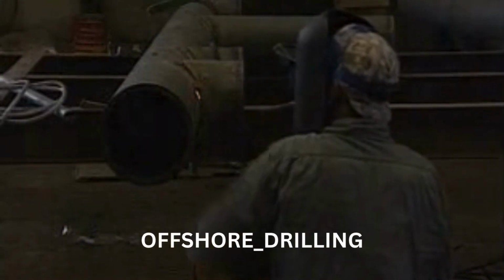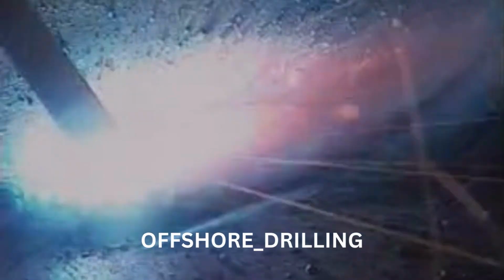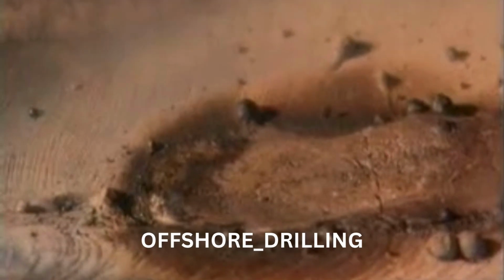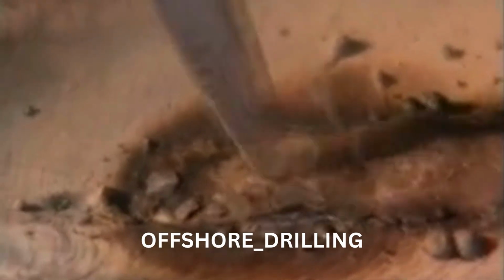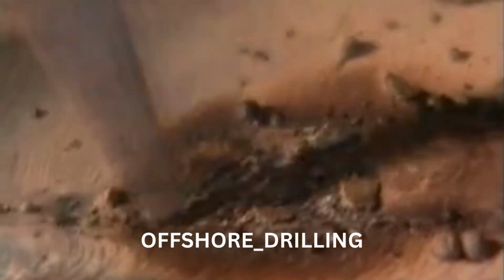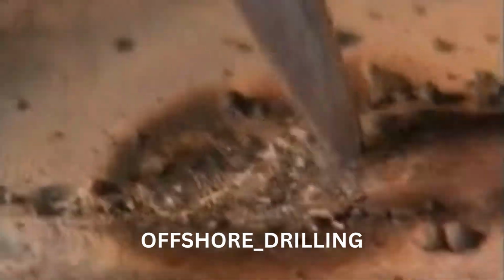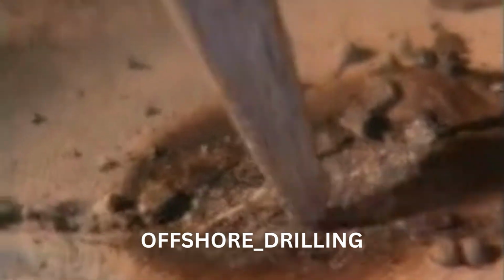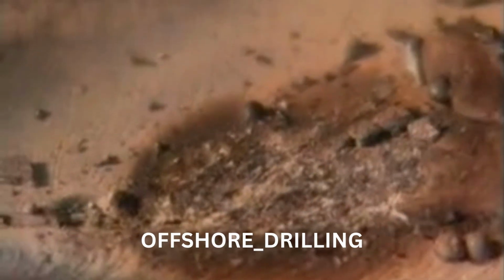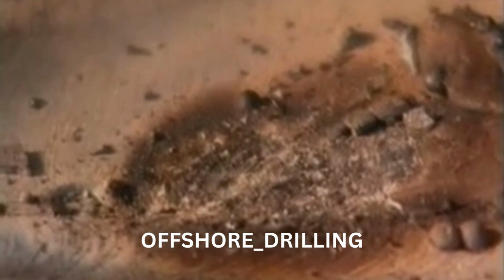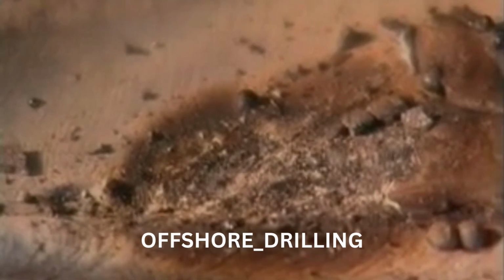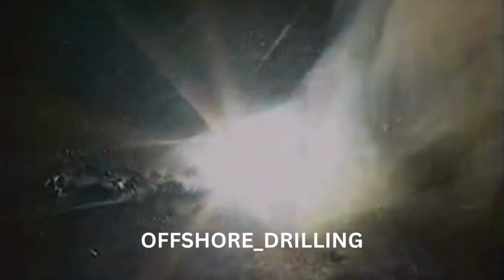Often, the electrode will be exhausted before you finish the joint. When you break the arc, it leaves a crater at the end of the weld, which can create problems. Because the crater contains less filler than the rest of the weld, it cools more quickly and can cause cracks to appear. Before you strike the next arc, you should clean off the last inch or so of the weld to prevent inclusions, but you can leave the rest of the weld with its protective layer of slag. Then make sure the crater is filled to match the previous bead before continuing along the joint.